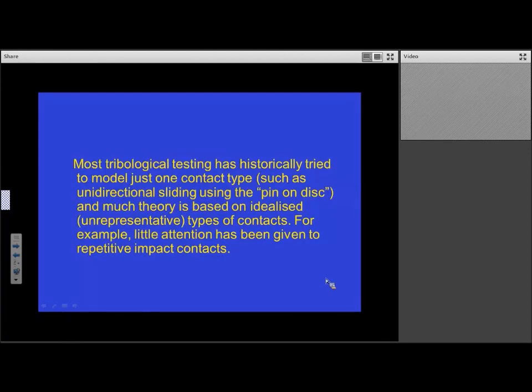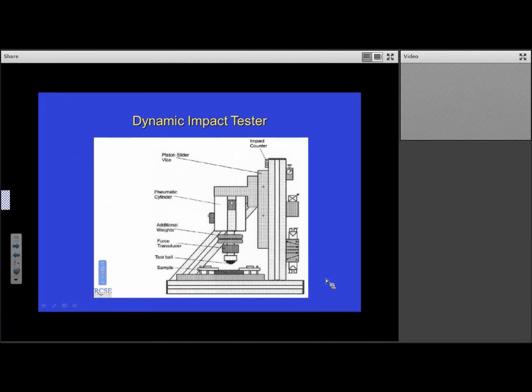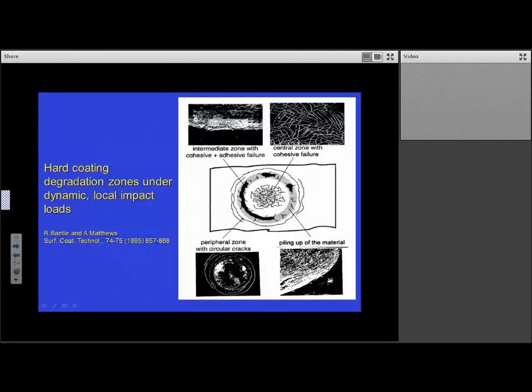I would say that most tribological testing has historically tried to model just one type of contact, such as a unidirectional sliding contact, like a pin on disc. And much theory, including Archard's, is based on rather unrepresentative types of contact. For example, little attention has been given to repetitive impact contacts. We've looked at this, we've developed impact testers, and we've looked at the behavior that you get with different coatings under impact conditions. So this is a pneumatically operated impacting machine, and the sample would be here, and that would be an impacting, maybe a tungsten carbide ball hitting the surface at high frequency. And then we look at the nature of the failure under the impact area. You can get cracking in the indent region, you can get build-up around the indent, you can get cracking around the indent, depending on the coating and the different properties of the substrate and the coating.